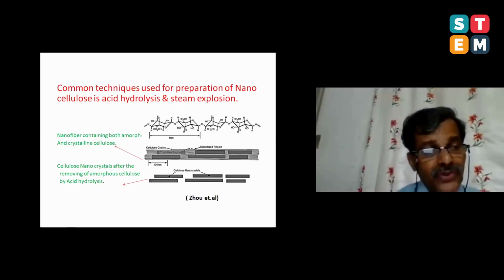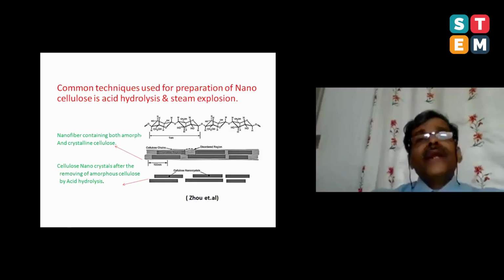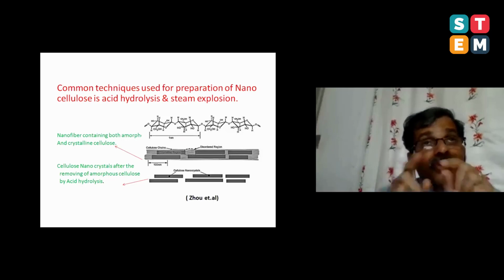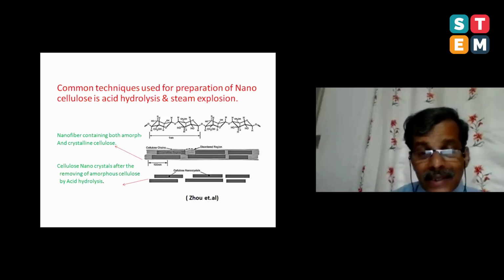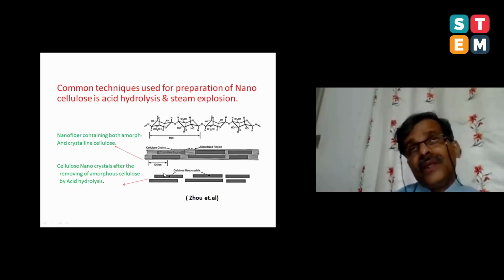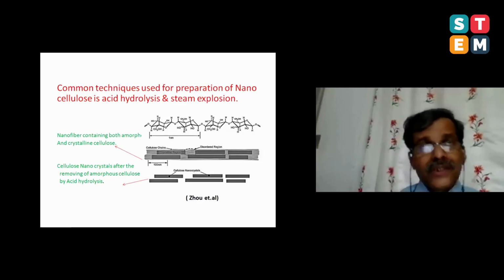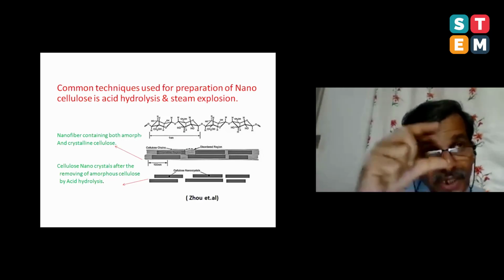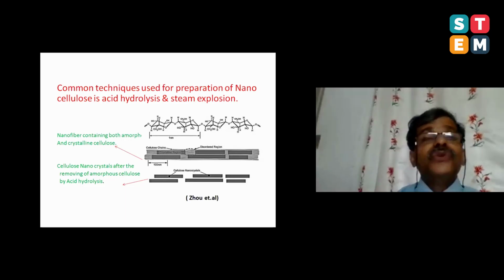So you have the possibility to make either long nanofibers, where the length could be several microns, or short nanocrystals like this, where the length could be 100 nanometer or 200 nanometer. Of course, the diameter depends on the nature of your starting material. It could be in the range of 1 to 50 nanometer.